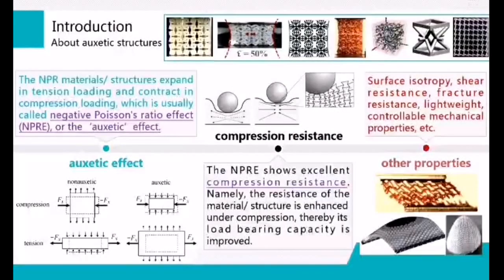Compared with the NPR structures, the energy absorption of the traditional structures is still not good enough because the NPR structure can realize the abnormal phenomenon of compression contraction or tension expansion. Therefore, it can produce indentation resistance to greatly improve the mechanical properties and energy absorption. These pictures are NPR structures or materials, and it can be found that the NPRE of compression contraction is indeed realized. Besides, the NPRE can also contribute to anti-shear, anti-fracture, and other effects, but we now focus on the compression properties.